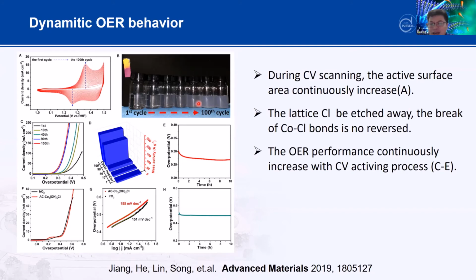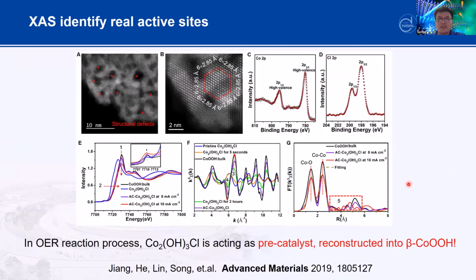So if we understand, by the control sample, we can see that during the reaction the lattice chloride will be etched away by the reaction. So the breakdown of the cobalt chloride bonding will never be reversed, because the chemical reaction forbids it, right? In this case, the OER performance continuously increases with the CV activating process. So here we try to understand what happened.